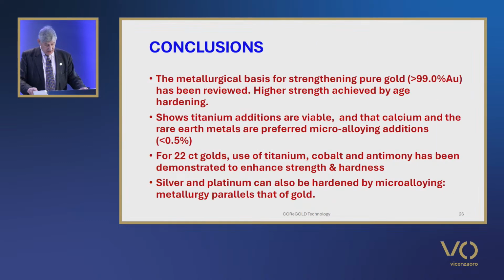So we can just come to my last slide. I think we can conclude that the metallurgical basis for strengthening and hardening 24-karat gold of at least 990 fineness has been reviewed. This shows that as well as titanium additions, calcium and the rare earths to be the preferred microalloying additions, but other possibilities have been noted.